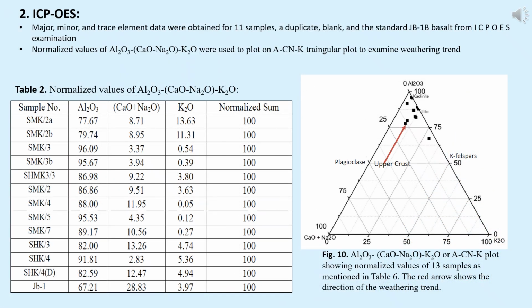Major, minor, and trace element data were obtained for 11 samples, a duplicate, blank, and the standard JB1B basalt from the ICP-OES examination. From this data, values of aluminum oxide, calcium oxide, sodium oxide, and potassium oxide were normalized and plotted on a A-CN-K triangular plot which shows weathering trend. The direction of the red arrow from plagioclase towards kaolinite and illite explains their abundance in the shale sample.